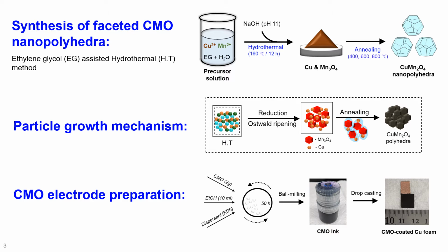Therefore, in this work, we are focusing on synthesizing faceted CuMn2O4 nanopolyhedra via the ethylene glycol, that is EG, assisted hydrothermal HT method. Initially, we took copper chloride and manganese chloride as precursor materials in a 1:2 ratio. These two are mixed together in a solution of EG and DI water, where 50% is EG and 50% is DI water. Now the color of the solution is pale blue, and then 5 molar NaOH has been added to the solution to fix the pH at 11. At pH 11, the color of the solution is completely different, which is brick brown.